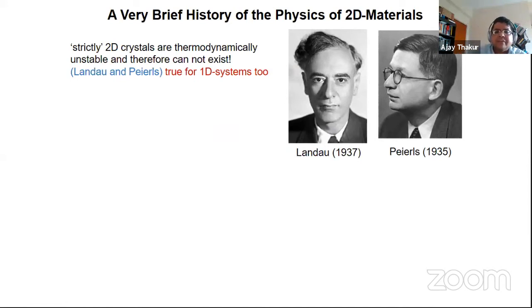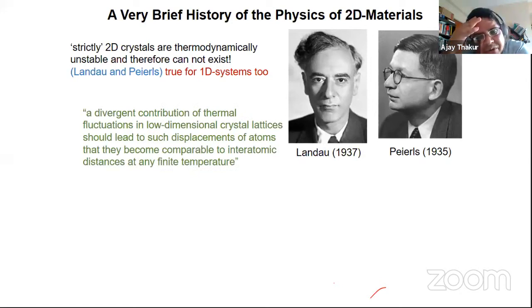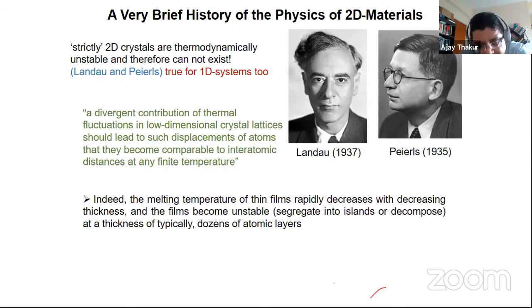So to summarize very briefly the history of physics of 2D materials, initially, strictly 2D crystals were supposed to be, or were in fact shown to be, thermodynamically unstable. And therefore, there was a strong proposition from the likes of Landau and Peierls and a whole bunch of other researchers who followed suit, that in fact 2D crystals will not exist. And the same argument also went forward to be true for 1D systems. So in fact, what happens is there is a divergent contribution of thermal fluctuations in low dimensional crystal lattices, and that leads to displacements of atoms which are larger than the atomic spacing, interatomic distances, at any finite temperature. And therefore the material system is unstable. And that leads to essentially a melting of the so-called 2D material.